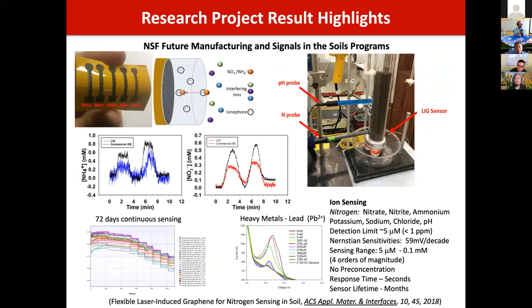We've also developed with NSF a lot of different fertilizer ion sensing, looking at them in soil columns and comparing them to conventional liquid junction electrodes that you could buy for $300 to $500. And we get fairly similar results to those commercial sensors. Ours also just seems to last longer. It's more robust. We don't have to fill in electrolyte solution behind an ion selective membrane, but we put the ion selective membrane right onto that surface of the graphene, so we don't need to regenerate it. And that way we can have it last for up to 2 months. Here's 72 days of continuous sensing. And that means this could be something that could be put into the field and potentially used for continuous monitoring. We've also looked at some heavy metals as well.